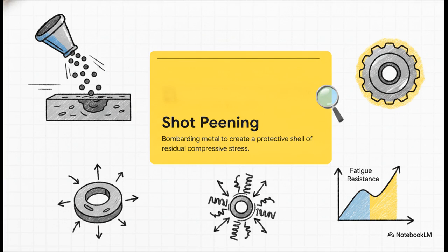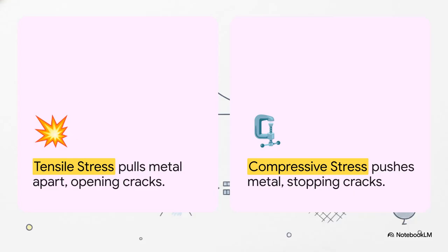Millions of these tiny dents overlapping create a highly hardened, compacted shell around the part. We are essentially beating the surface into a state of permanent residual compressive stress. The basic physics of why that violent bombardment actually works is just fascinating. See, fatigue cracks require tensile stress to open up and grow. Tensile stress wants to pull the metal apart, but shot peening creates compressive stress on the surface. Compressive stress actively pushes the metal together.